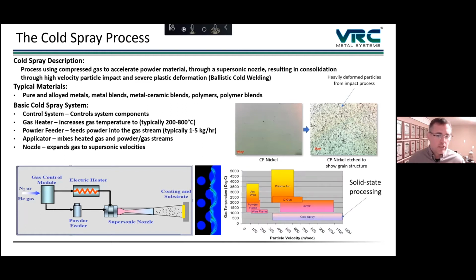Now, I said before, this is a solid state process, and that's really important as we go forward through the discussion, because unlike your thermal spray processes where your materials tend to melt and then re-solidify when they impact on the surface, these particles are impacting relatively cold, well below their softening or melting points. And that ends up causing severe plastic deformation, which is where kind of all the magic happens. That's where the bonding is occurring, and that's how you're getting good interparticle bonding as well.